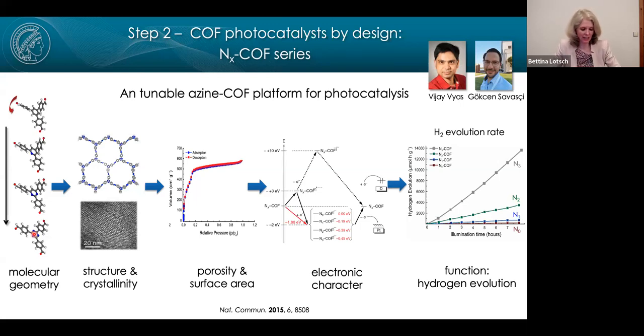So for example, when we look at the carbon nitrides, or COFs are actually fairly similar, most of them, we would look at photoluminescence lifetimes in the low nanosecond range, even below the nanosecond range. What we see, from a recent study on carbon nitrides and PHI, is that we can distinguish between lifetimes that are modified by charge trapping and those that are more bulk or intrinsic. The intrinsic ones are typically shorter, in the sub-nanosecond range, and those that are modified by the traps are longer.